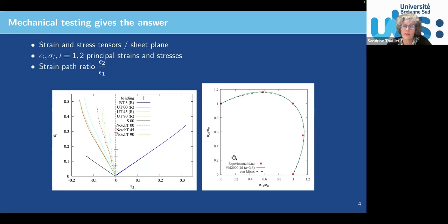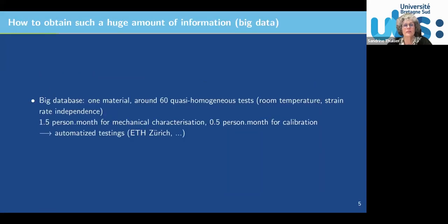You have a similar representation in the stress space, using the components of the stress tensor. But for reaching such information, you need some data. And from this, you may have two different trends. One is what I call big database. So for one material, if you want to characterize in tension, in shear, in hydraulic bulge test, in plane strain tension, up to rupture, you may have to do, and this is my own calculation, around 60 quasi-homogeneous tests, and maybe up to 100 if you consider including reverse strain path change.